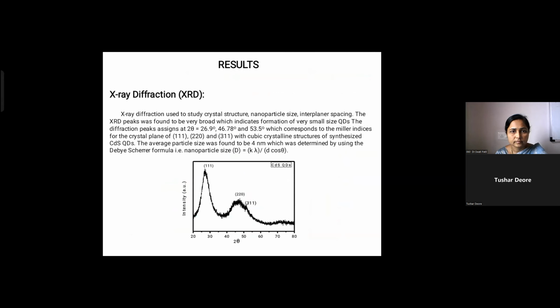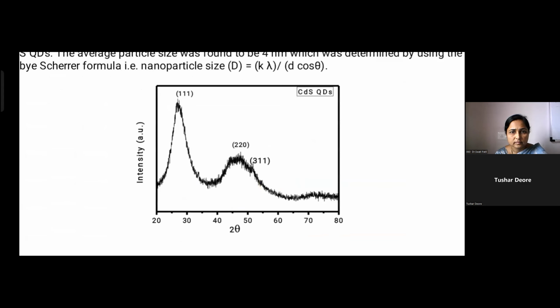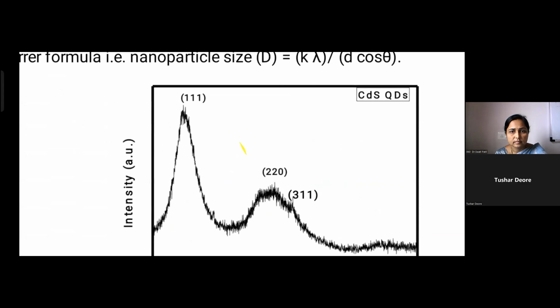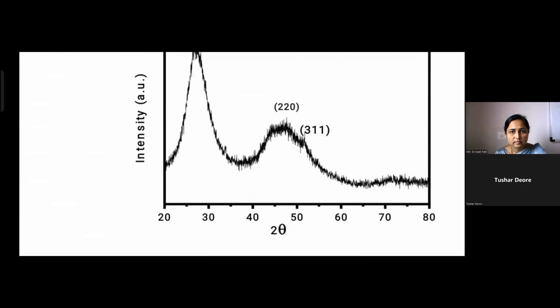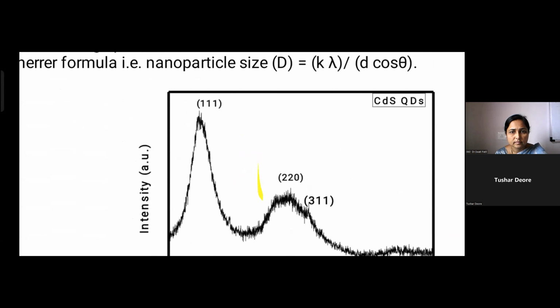My first characterization, ma'am, is X-ray diffraction. From X-ray diffraction, we can analyze the crystal structure, nanoparticle size, and interplanar spacing. The XRD peaks were found to be at 26.9 degrees, 46.78, and 53.5 respectively. And then by using the Debye-Scherrer method, D is equal to K lambda divided by beta cos theta, where beta is the full width at half maximum, I determined the average particle size, which is 4 nanometers, ma'am.